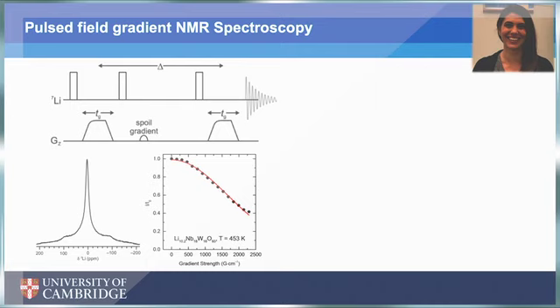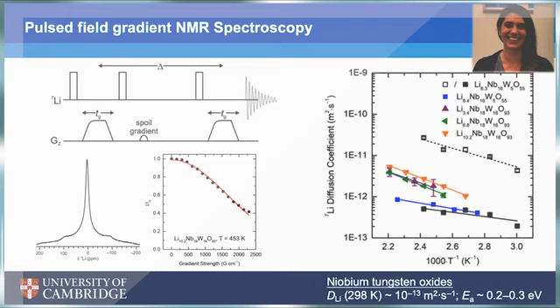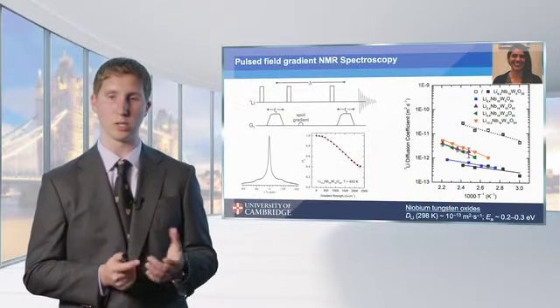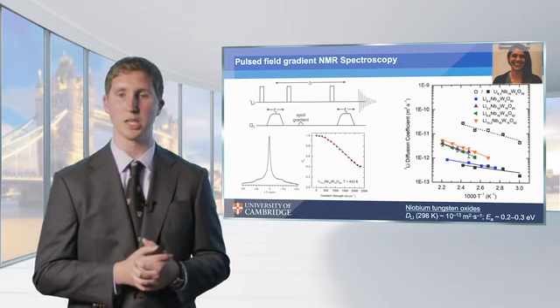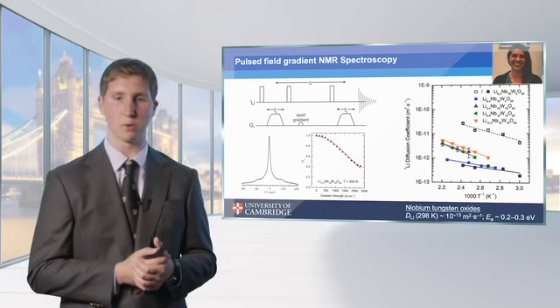And so that's what this graph in the bottom left shows, is that as we increase the gradient strength, we have less and less intensity. And we can do this as a function of temperature. We can do this as a function of state of charge. And we can try and work out what the diffusion coefficients and the activation barriers for lithium hopping between the different sites would be. And so in this case, we find that the room temperature lithium diffusion is something around 10 to the minus 13 meters squared per second. And it's characterized by a pretty low activation energy barrier of 200 to 300 meV. This was all work that was pushed by Lauren Marbella in our group, who is now an assistant professor at Columbia University, carrying on the development of PFG NMR methods.